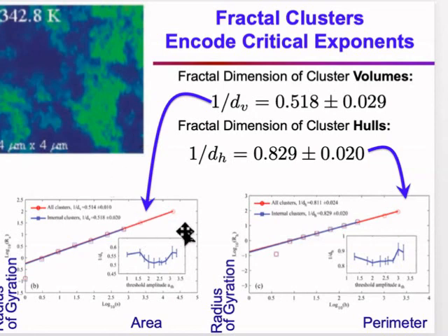So here, for example, let's focus first on the volume fractal dimension. We map each of these areas to a particular cluster, green being metal. And so we look at the structure of these clusters and count, for example, how many pixels are present in a cluster of a particular size. So that would be area here. So this is area on the horizontal axis.